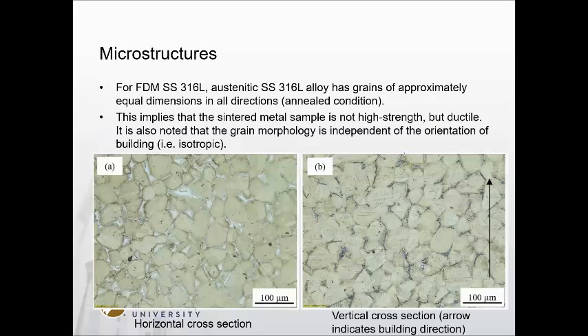Okay. After that, the part is sectioned for microstructure characterizations. The part is sectioned vertically and horizontally. So there are pictures to show the microstructures of the cross section. As you can see, all the grains have similar dimensions in all directions after the sintering process. We can consider this to be an annealed condition for the stainless steel 316 alloy. And for the second picture, the arrow indicates the building direction.